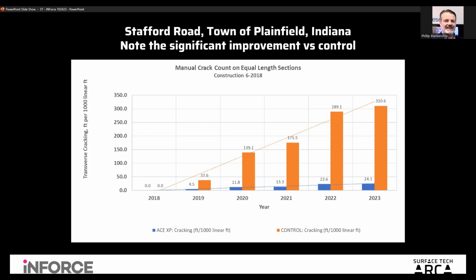Yeah, glad to do that. This is just where we went out, and this is not a PCI value. If I went out and looked at the actual PCI on this, you've got about 8 points different on the pavement condition index. Some people call it a pavement rating index, which looks at all the different components. But this is just looking at transverse cracking, and transverse cracking, of course, is that early indicator of long-term performance. This roadway is an airport access road just outside of Indianapolis Airport, not too far from Indianapolis 500 that you may have heard about, where they do a little racing out there.